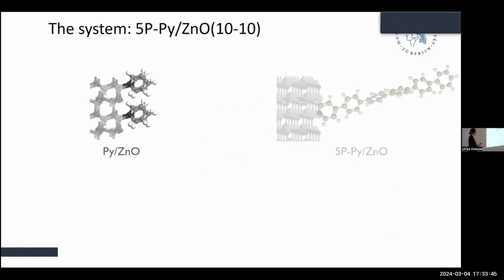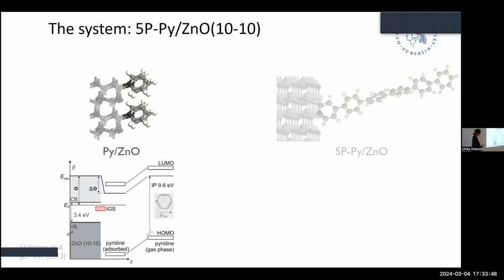We did some spectroscopic analysis. For pyridine, you have, however, a different energy level alignment. As it's just one ring, you have a very wide band gap, and actually it has a negative electron affinity. And when you put it onto zinc oxide, the bond formation of the nitrogen with the zinc oxide and the permanent dipole moment of the pyridine together lead to a gigantic reduction of the chemical potential down to 1.9 eV. Normal work functions are somewhere between 4 and 5 eV.